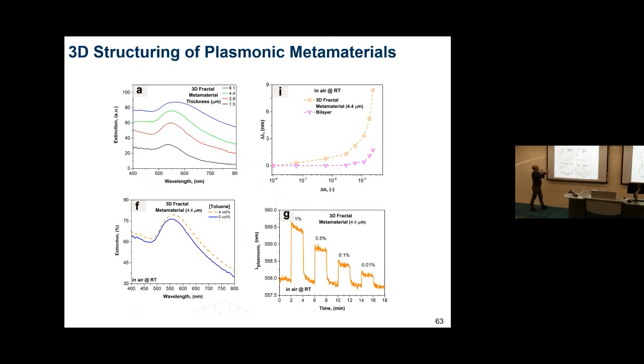It's interesting that the width of the peak does not change much up to 2.9 micrometers, although the absorbance changes. Then we start seeing interesting effects like widening and so on.